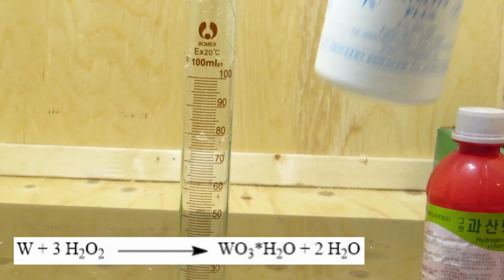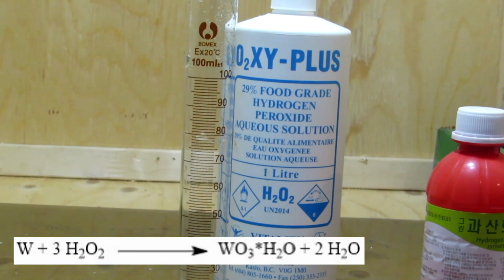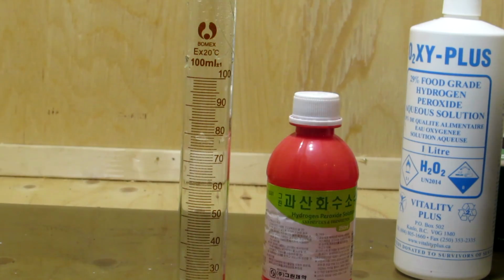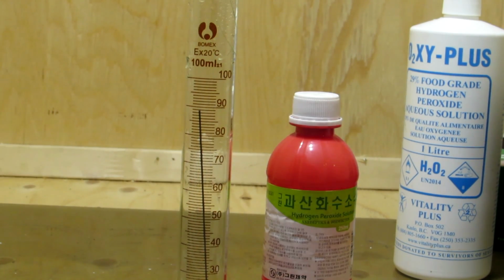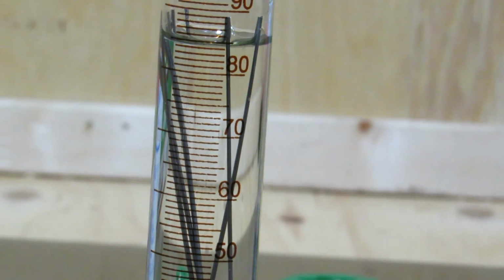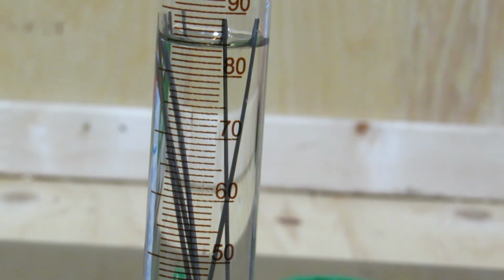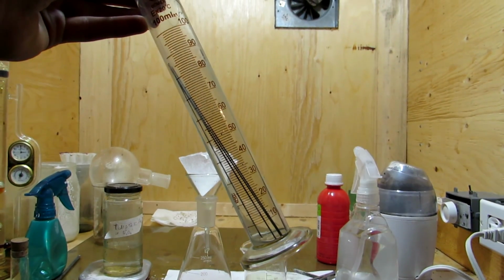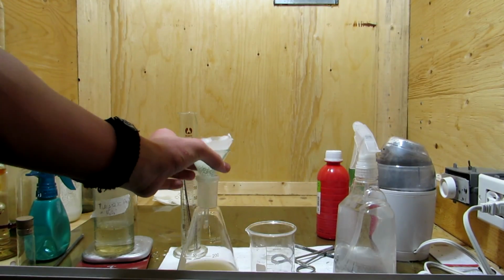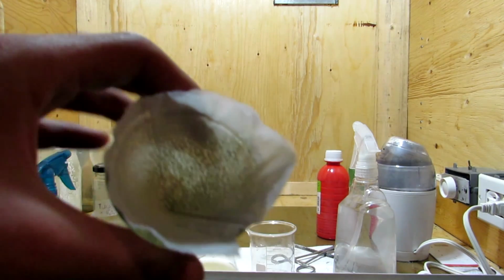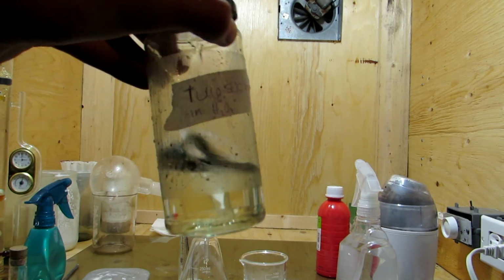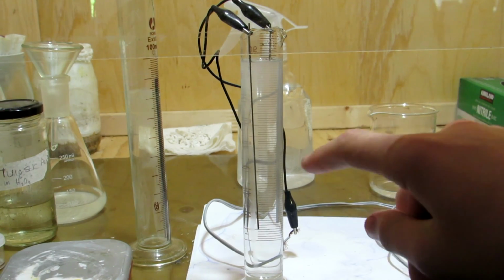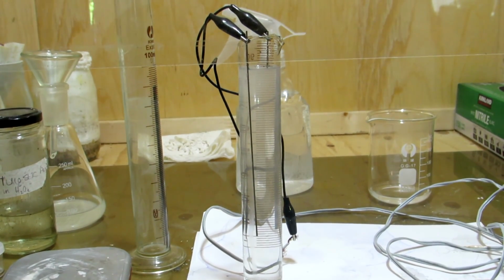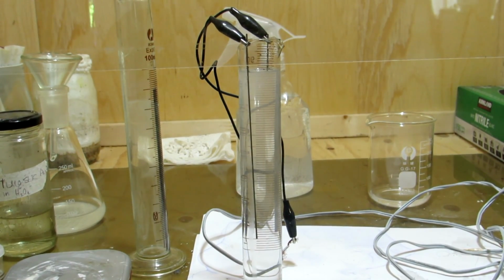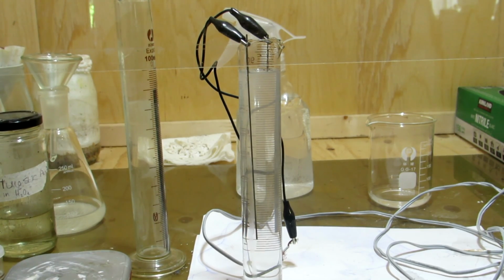Tungsten will dissolve in hydrogen peroxide to form tungstic acid, so the initial thought was to dissolve away the tungsten, leaving the thorium dioxide. After placing 5 rods in a graduated cylinder and leaving it in 30% hydrogen peroxide for 2 months, however, only 2 grams of the rods dissolved. I filtered the solution to obtain a bit of thorium dioxide that was liberated, and then saved the tungstic acid solution. To finish processing the rest of the rods, however, we will use an electrochemical method to dissolve the tungsten, as the hydrogen peroxide is too inefficient.